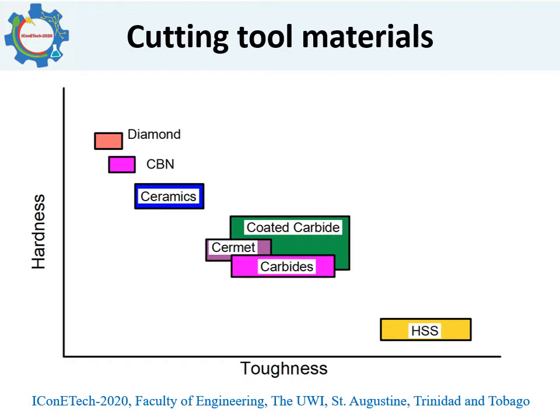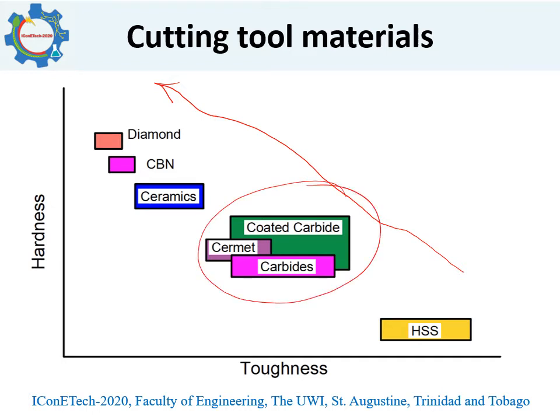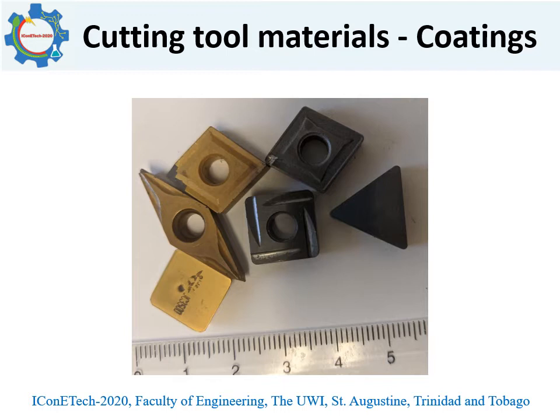Now, historically, a large number of cutting tool materials have been developed, starting with the early 20th century high-speed steel to other materials such as diamond and CBN, ceramics and carbides. Of all these materials, because of the better hardness and toughness combinations, the carbides are one of the most extensively used tool materials in the industrial scenario, so that contributes to carbides and coated carbides. As you can see, the range of coated carbides is much better than either carbides or ceramics. Visually, you can see that coated carbides have color, whereas the uncoated carbides do not have any color that you can associate with them.